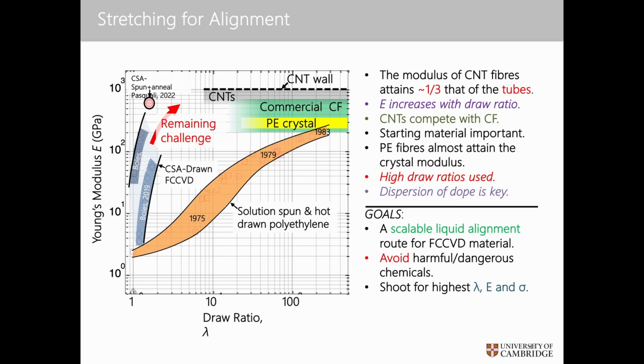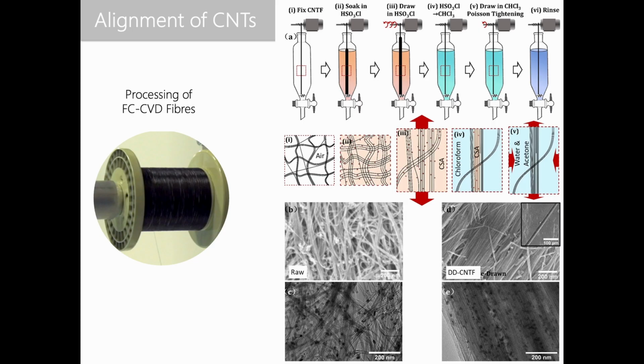So if we look at what the polymer community did to get carbon fibers, from the late 60s to the early 70s, they got better and better at drawing these materials out, and as they drew them out, they aligned them better and better. And you can see that they're at draw ratios of over 100, and that gets you to these commercial scale carbon fibers and the very high-end military grade fibers that I talked about right at the beginning. We're only in the infancy there, and so we're getting substantially high strengths and modulus, but yet we're nowhere near the draw ratio. So I have a lot of hope that with better techniques to draw these materials out, we will achieve better and better material properties there.